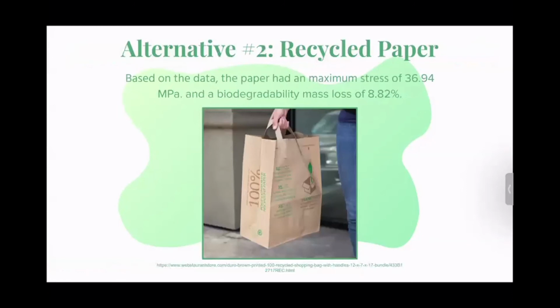The next best alternative would be the recycled paper. Since the recycled paper had the second highest of the four percent mass losses, it has potential to become a more sustainable barrier material compared to polyethylene. The mass production of the recycled paper also makes it easily accessible and realistic to the purpose of this research. Recycled paper also had a higher tensile strength than the cornstarch-based bioplastic, with its highest maximum strength, therefore making it the next best alternative of the barrier materials tested.